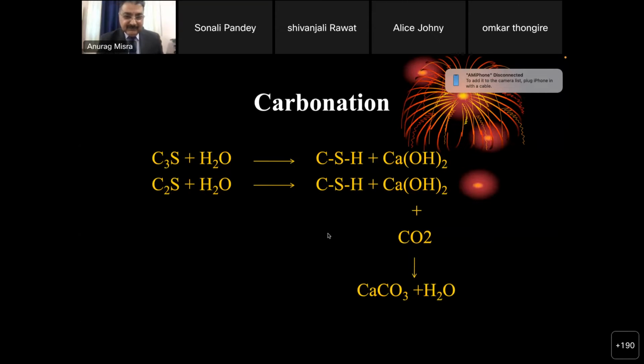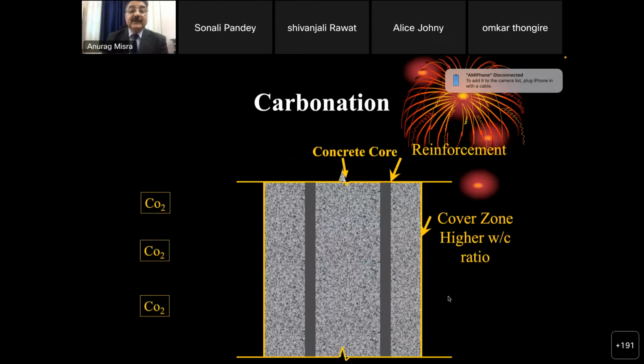The second mechanism I mentioned is carbonation, which is when the cement is hydrating, in addition to the calcium silicate hydrate, calcium hydroxide forms, which is attacked by the carbon dioxide from the atmosphere. CaCO3 is formed, and this also has a tendency of leaching out. When it is leaching out, it leaves more pores, and there is a mechanism of a similar type to what you saw for chloride ingress: carbon dioxide reaches the surface of the concrete and tries to carbonate it. This carbonation is happening layer by layer from the cover, and as time progresses, more carbon dioxide diffuses in with the air, and the carbonation front starts to move towards the reinforcement.